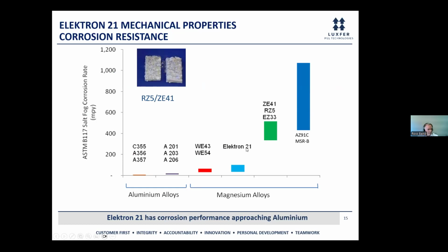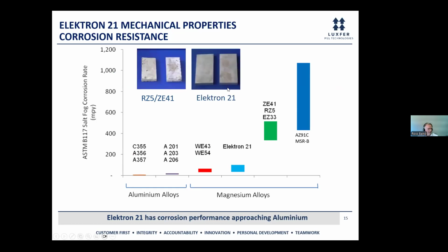But actually we've seen in recent years with WE43 and Elektron 21 corrosion performances that are approaching those of the aluminium alloys. And you'll see in the image on the left-hand side, you can see pitting after 10 days in a salt fog test, pitting in the RZ5 ZE41 material, and no such impact on the Elektron 21 material.